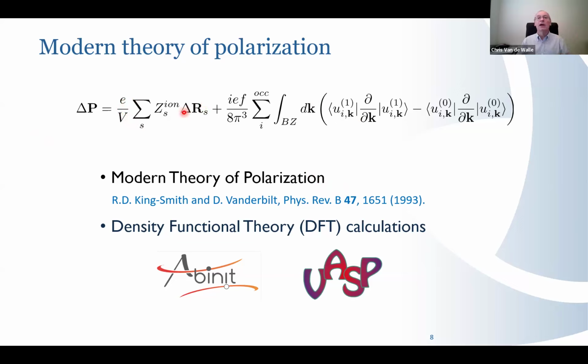So if you think of a gallium atom, all of the action usually is with the valence electrons. So you basically have an ionic charge of +3, and calculating polarization associated with that, you do in the way that I was describing in the hand-waving approach. But then the contribution due to the electrons, you need to carefully think through. And this expression is actually related to the so-called Berry phase approach, which interestingly also comes up when you try to calculate emerging materials like topological insulators, and you want to calculate invariants, etc. It's the same sort of integration over the properties of the electrons in reciprocal space. You integrate over the Brillouin zone.